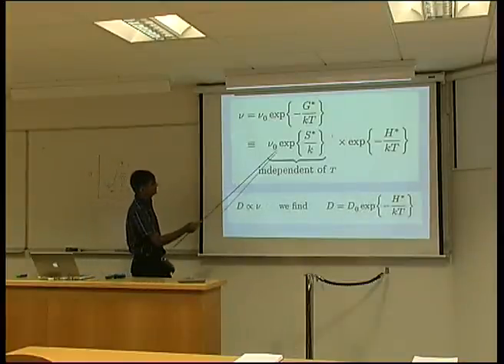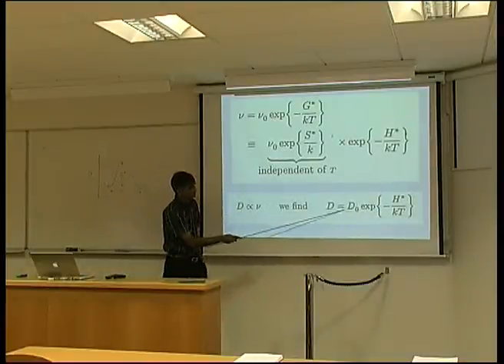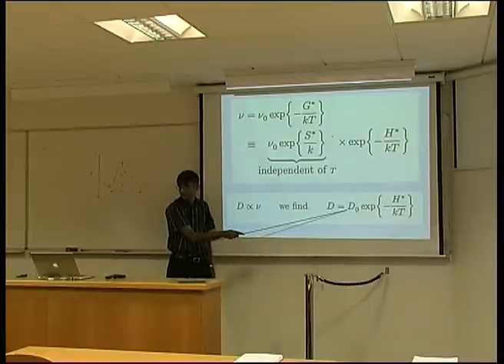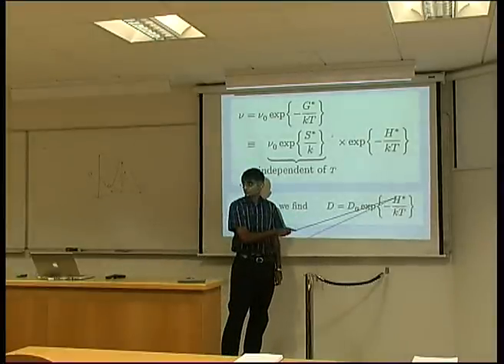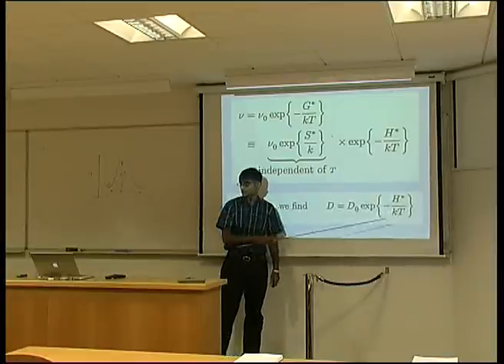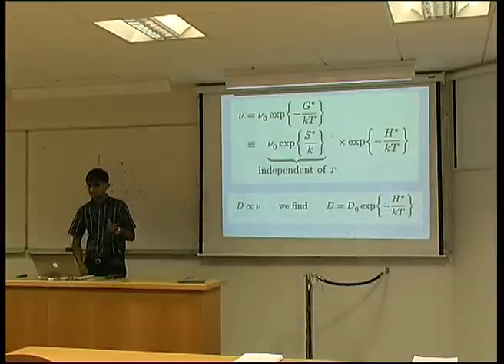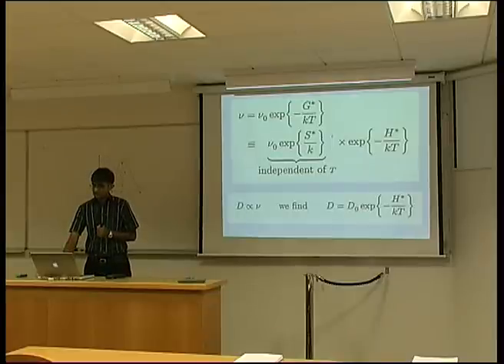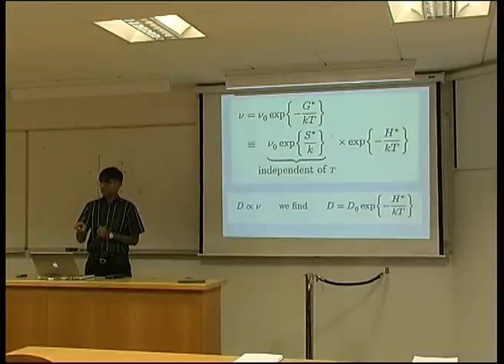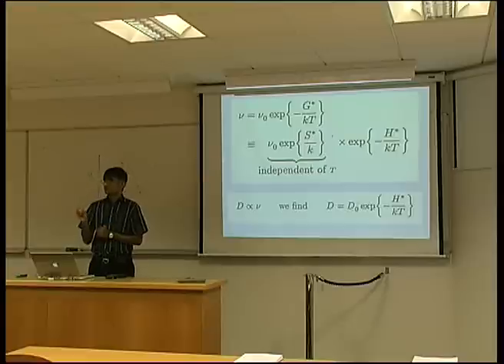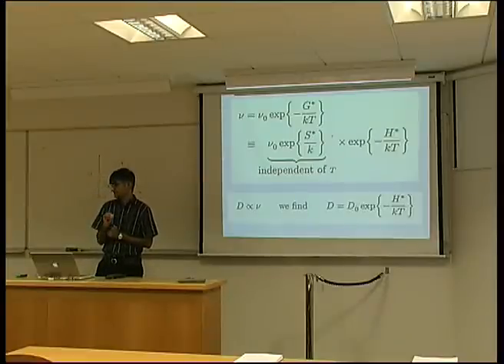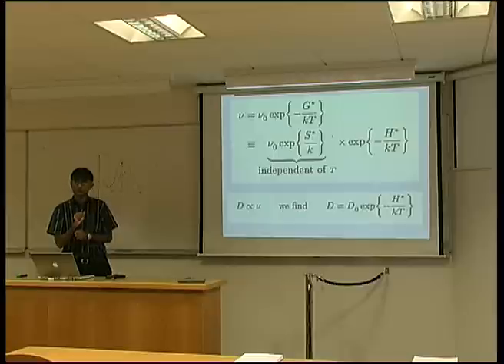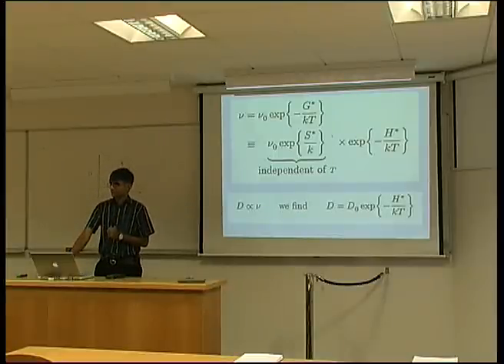So we could simply summarize this as D is equal to the temperature independent term D naught, which we call the pre-exponential factor, times e to the minus the activation enthalpy over KT. K is Boltzmann's constant and T is the absolute temperature. So this is how diffusion coefficients are defined by two terms. One is D naught, the pre-exponential term, and the other is the activation enthalpy, H star, which is often called a Q in a lot of the literature. So what we've defined is the temperature dependence of the diffusion coefficient.